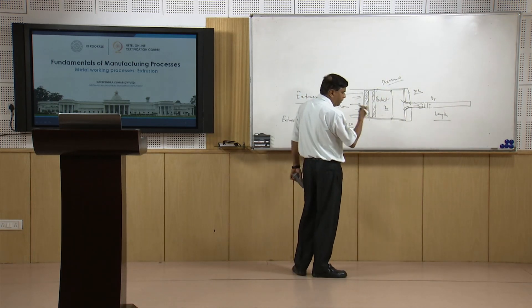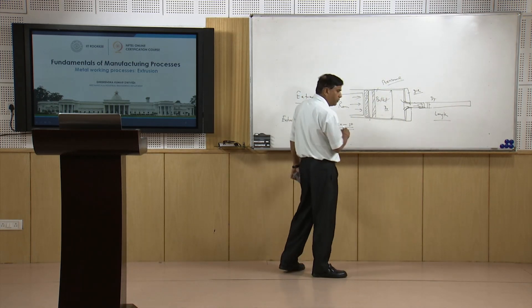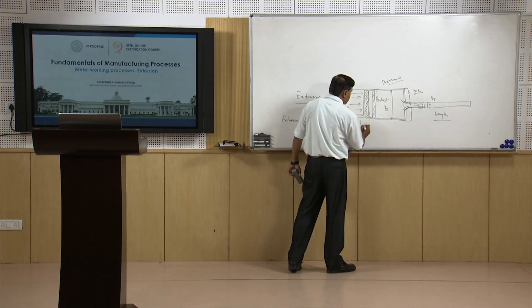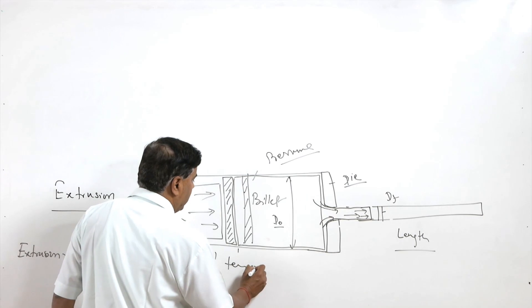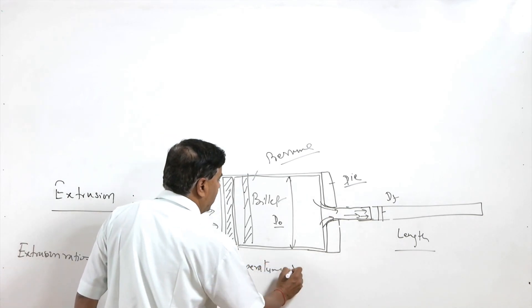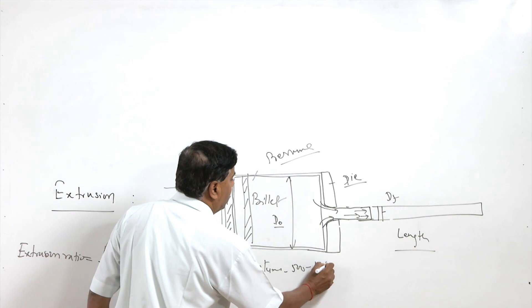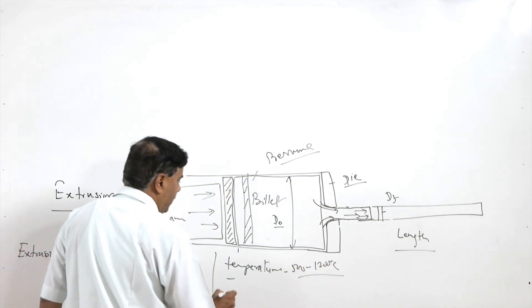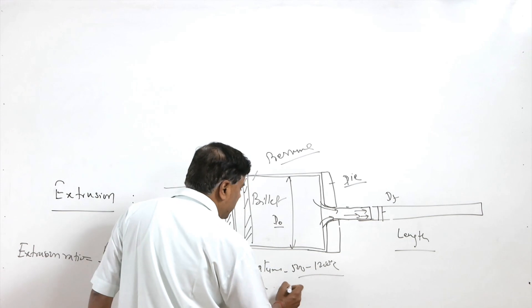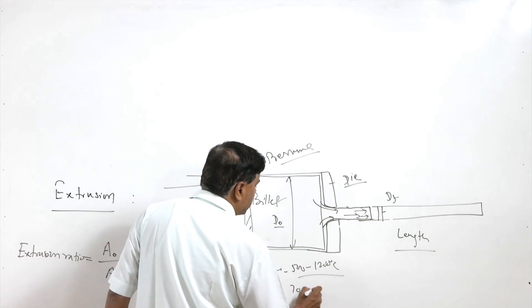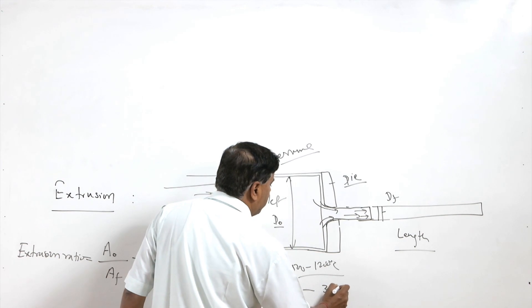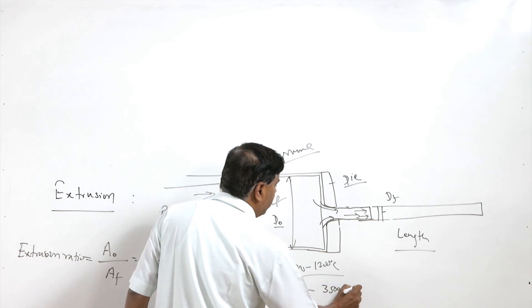Although the process can be hot or cold working type, normally the temperatures depend upon the metal — extrusion is carried out at 500 to 1200 degrees centigrade, using pressures ranging from 70 MPa to 3500 MPa.